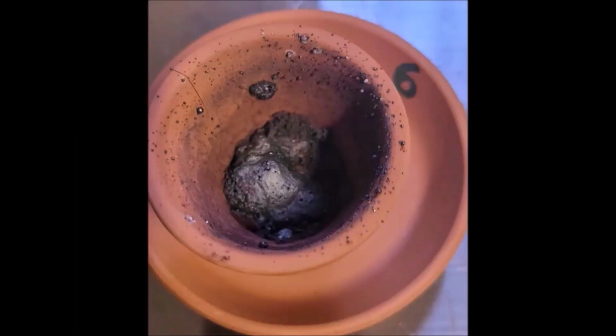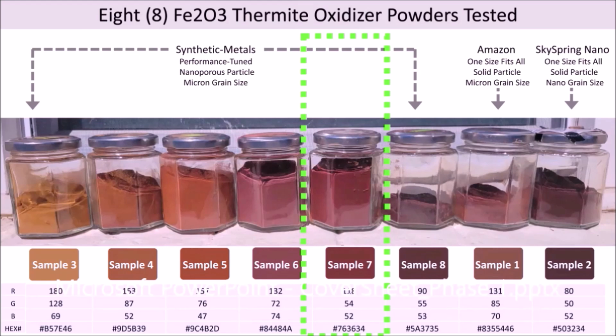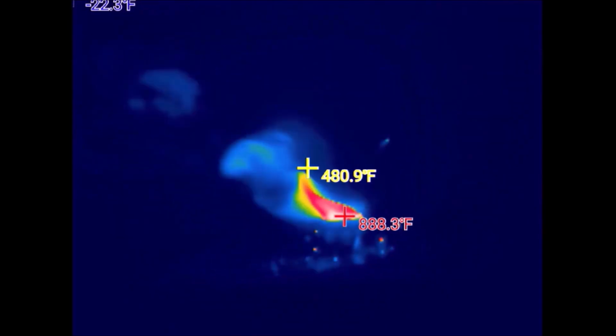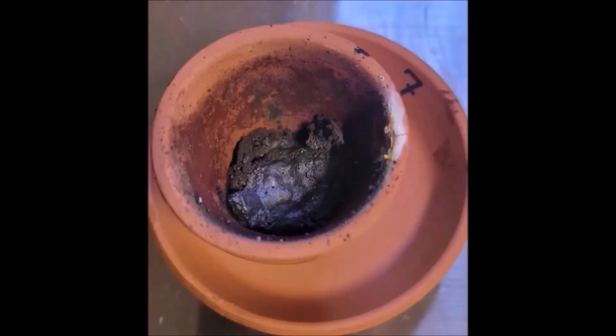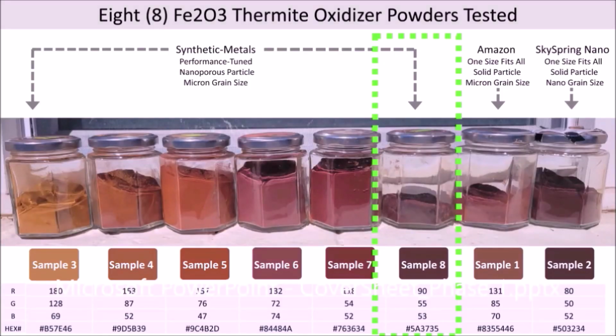The sample 6 afterburn is approximately 50% molten, 50% unreacted powder. The penultimate sample is sample 7 nanoporous powder. The sample 7 afterburn is approximately 70% molten, 30% unreacted powder. Last up, our darkest colored nanoporous particle.